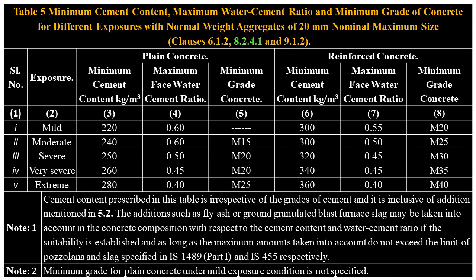M25. Serial number 3. Exposure, severe. Plain concrete, minimum cement content 250 kilograms per cubic meter. Maximum free water to cement ratio, 0.5, grade of concrete, M20. And for reinforced concrete, minimum cement content 320 kilograms per cubic meter. Maximum free water to cement ratio, 0.45, grade of concrete, M30. Serial number 4. Exposure, very severe.